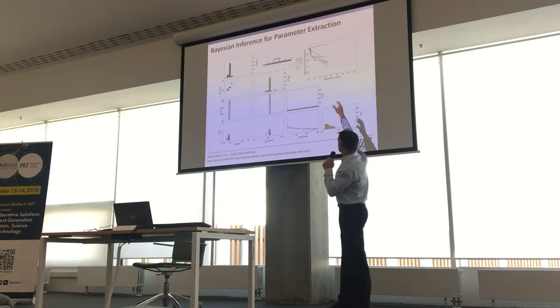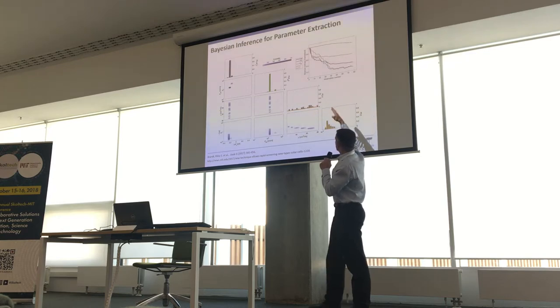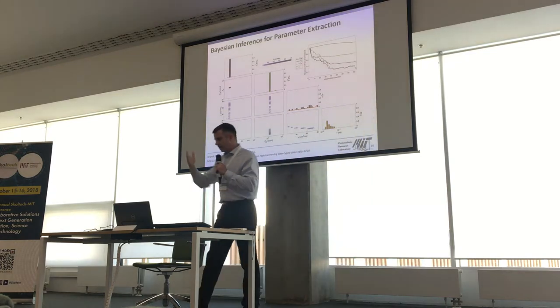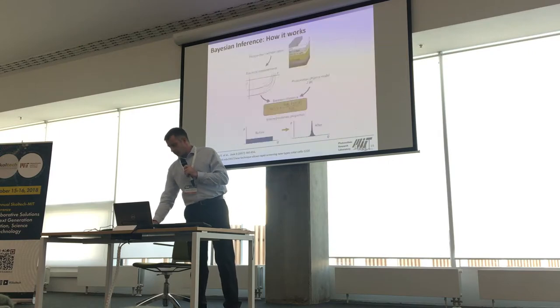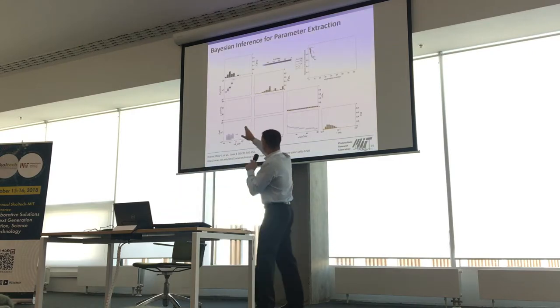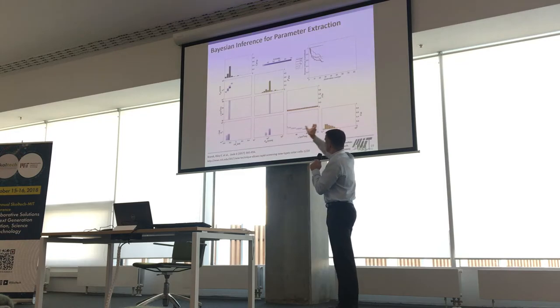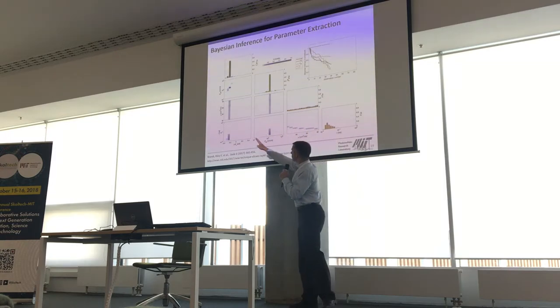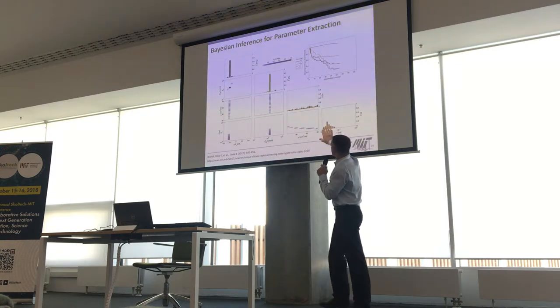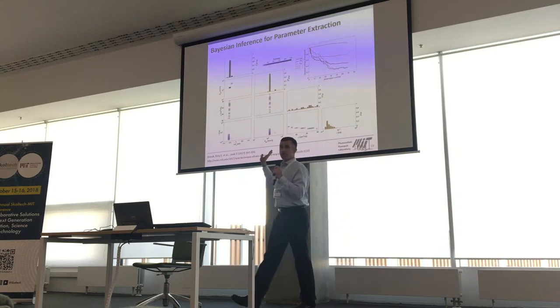And here's the data coming in real time. On the upper right, you see the entropy of each variable, each of those four, dropping with observation number. Meaning as we take more and more data into account, the entropy drops. And meanwhile, what we see is the probability distribution functions for the four different variables converging in some cases on singular values, in other cases on a limited range, and in other cases not converging at all.